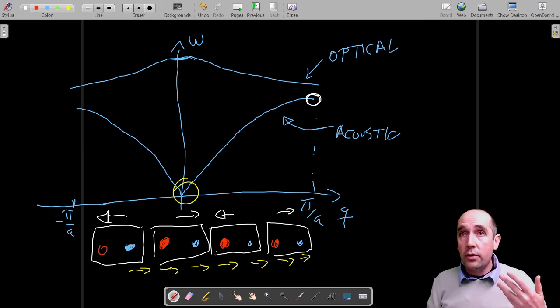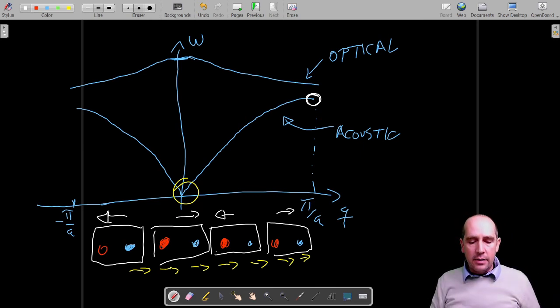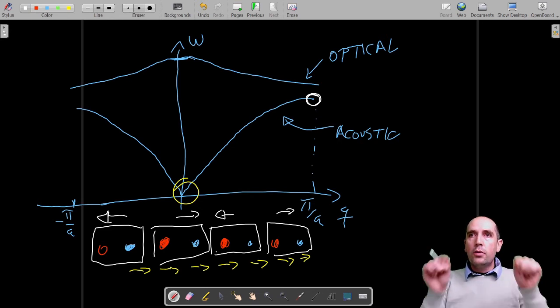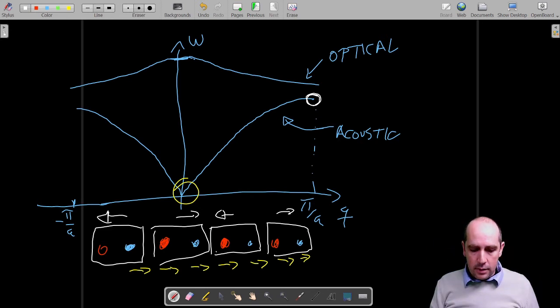However, there are additional vibrations in this particular case. If we had only one type of atom, these would be the only possible solutions, so the unit cell essentially comprises one atom. In this case, the unit cell has two atoms. So there are additional vibrations that we can think of, and these additional vibrations are essentially the ones that are related to motions within the lattice.